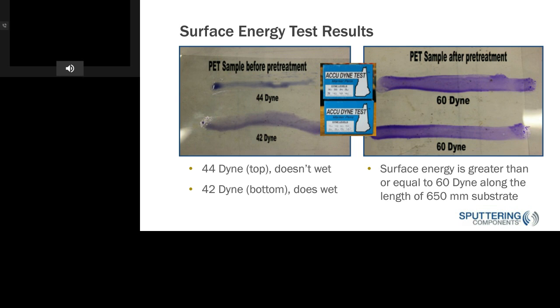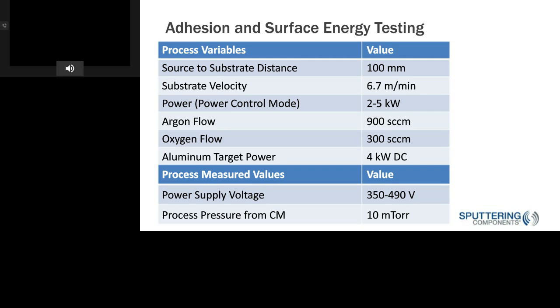Then we did further testing where we were looking at increasing the surface energy and then coating afterwards. So we did a slightly larger source to substrate distance of 100 millimeters. The substrate velocity was the same. The power was between 2 and 5 kilowatts. Argon flow, oxygen flow the same. And then the aluminum target power was around 4 kilowatts. We used a rotary aluminum target in the same chamber. Power supply voltage and the process pressure were the same too.